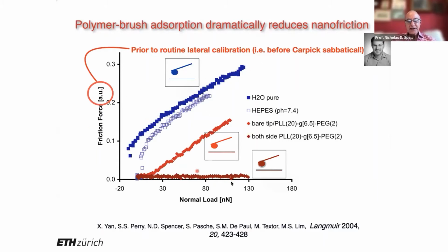So we see friction against load. So we're looking at the slope as a friction coefficient. And what we can see from this slope here is that we've got some friction in water and also in buffer solution in the case where we have no polymer present. When we have polymer on one side, we lose the adhesion component, but we still have friction. And when we have polymer on both sides, still in HEPES in this case, we can actually not measure the friction at all. So polymer brushes are extremely effective at lubrication. And in this experiment, we were actually below the level of detection of our AFM instrument.